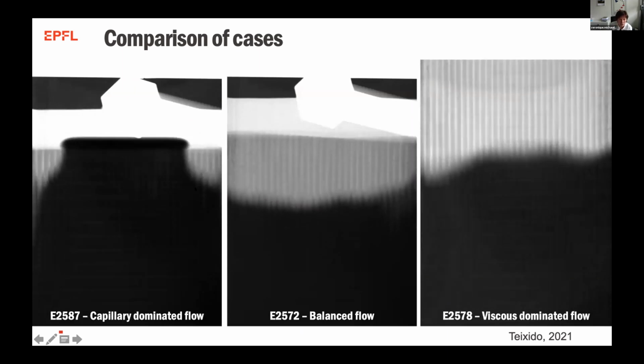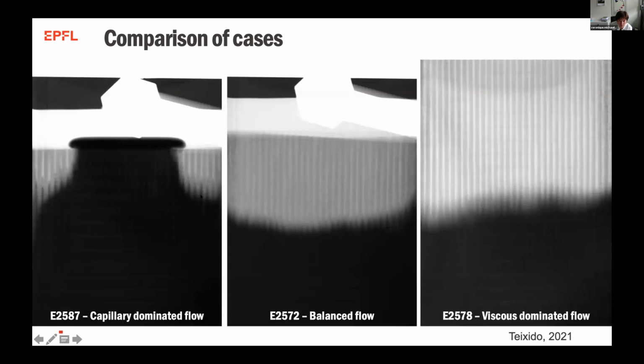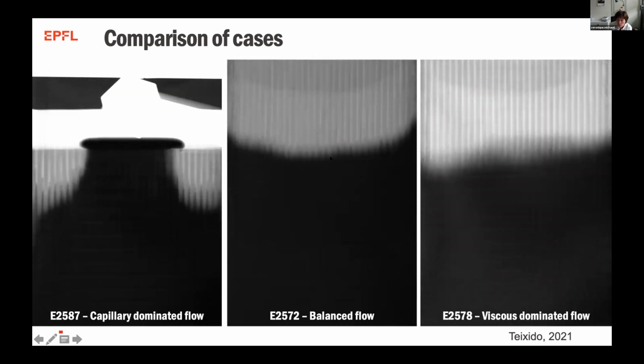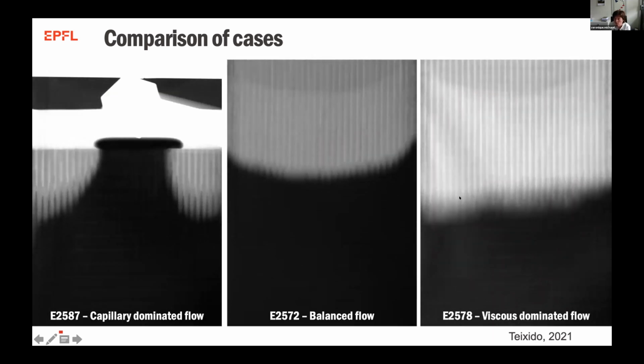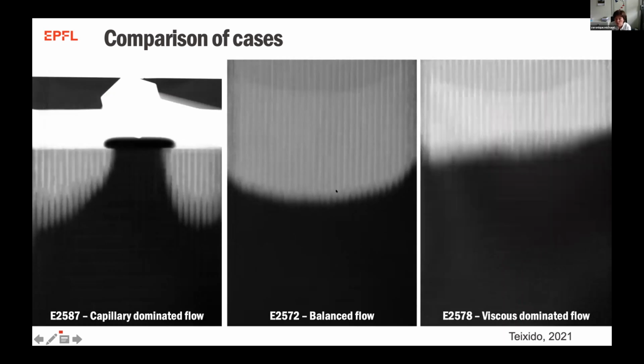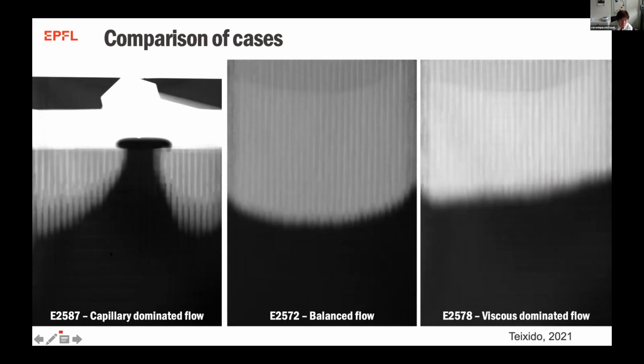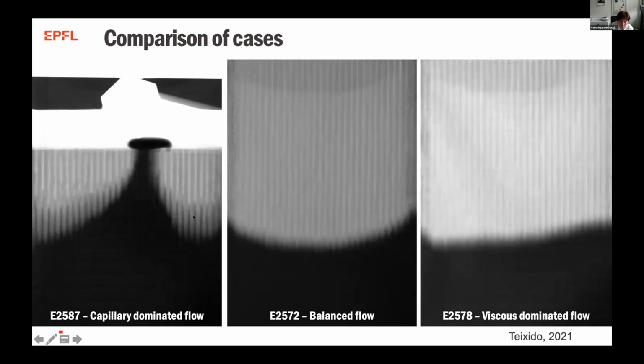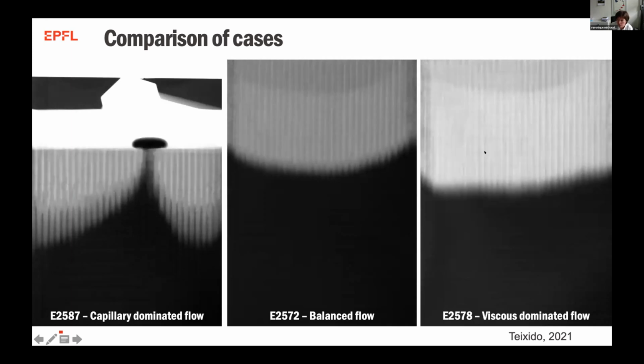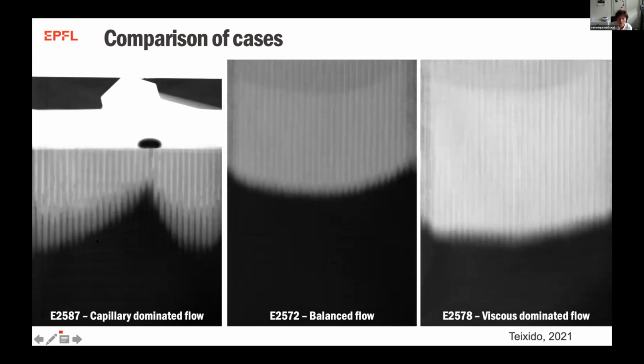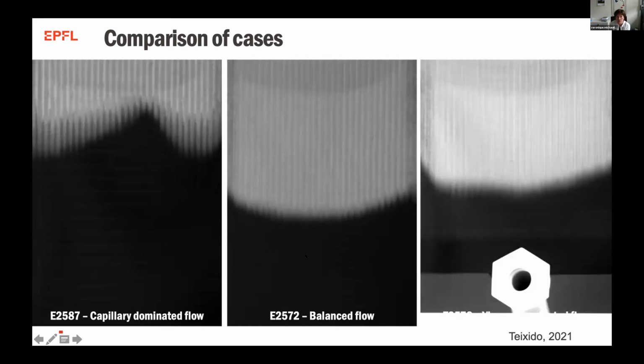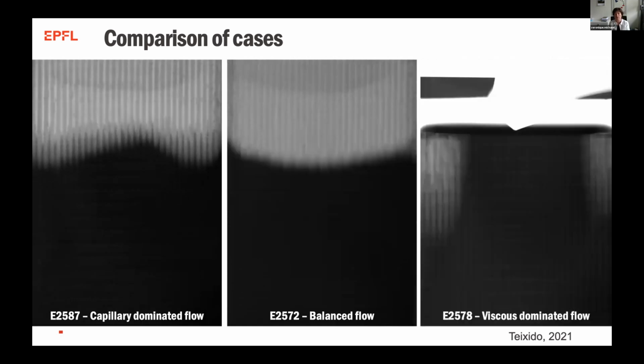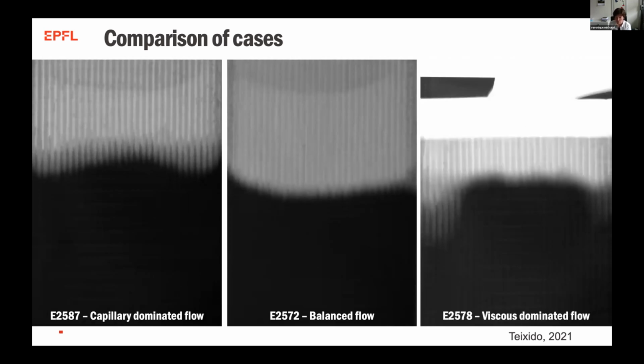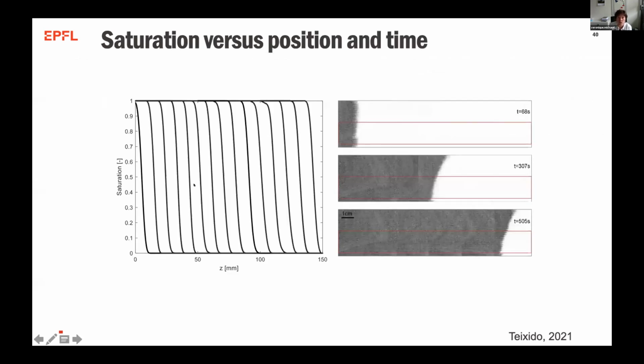So this is a capillary driven flow, where you see this is the balanced flow, and this is the viscous dominated flow. And in these cases, well, you need to do a lot of image analysis, and we're working on improving this. But you can see the difference in the flow front, depending on the different cases. And this is in a thick carbon fabric. Actually, the thicker it is, the better for this phase contrast. So it's good. And then you can measure saturation versus position and time.